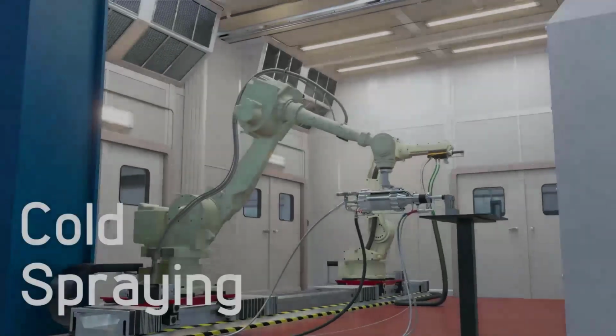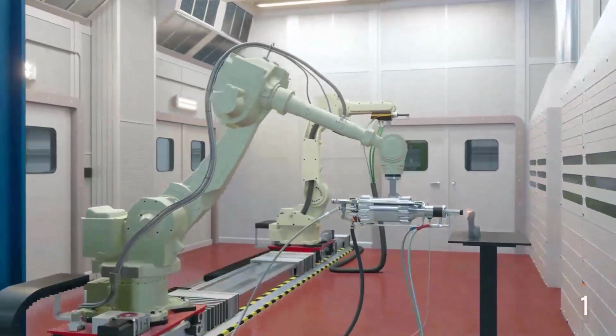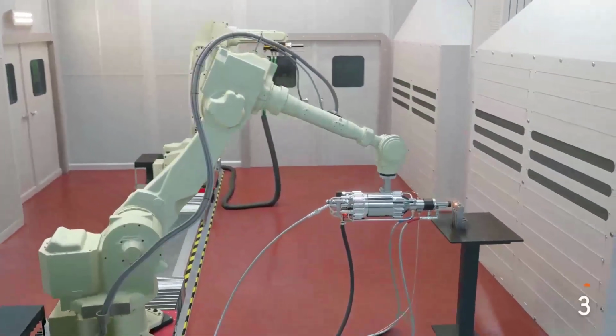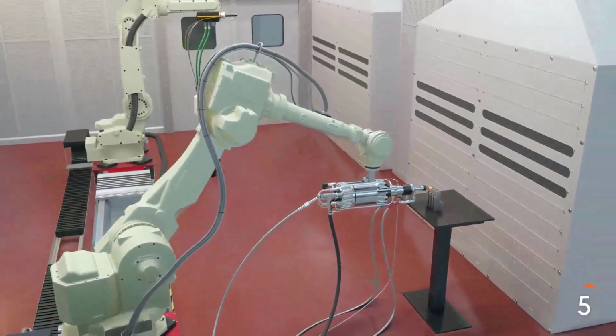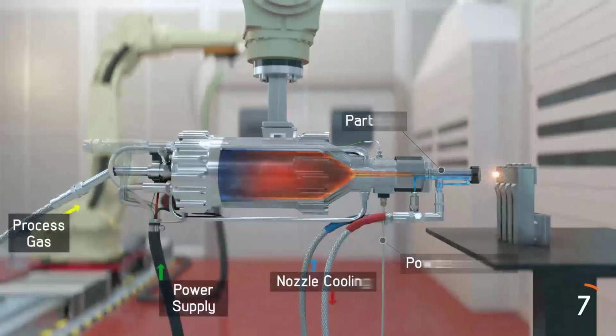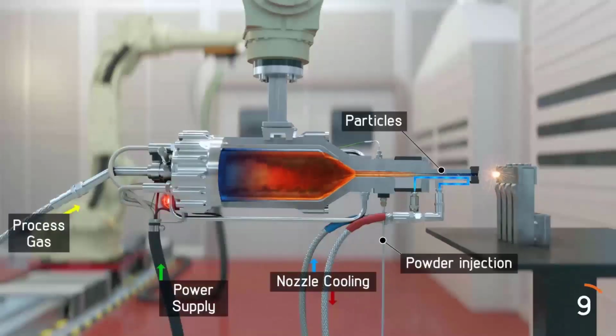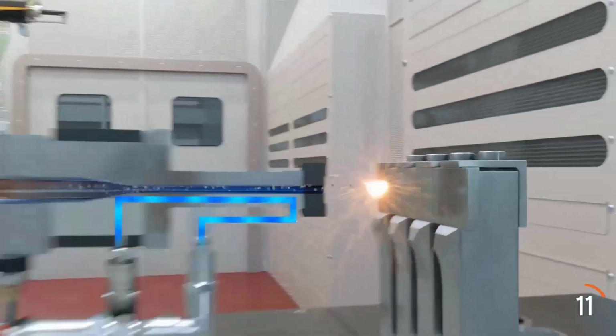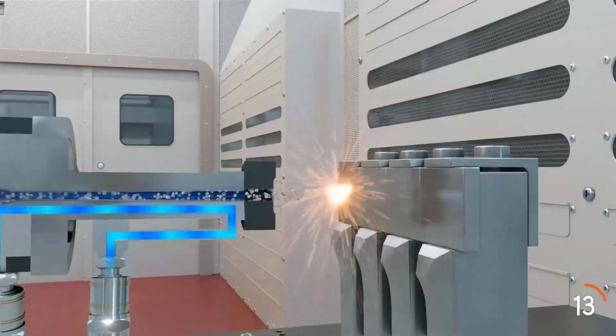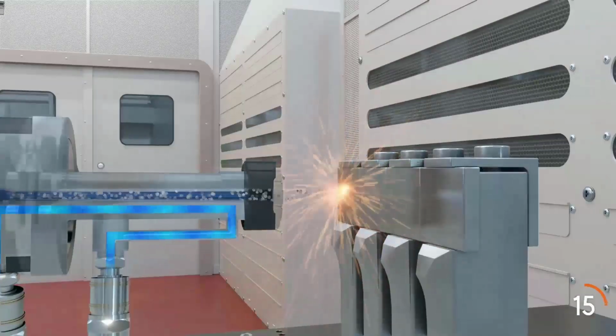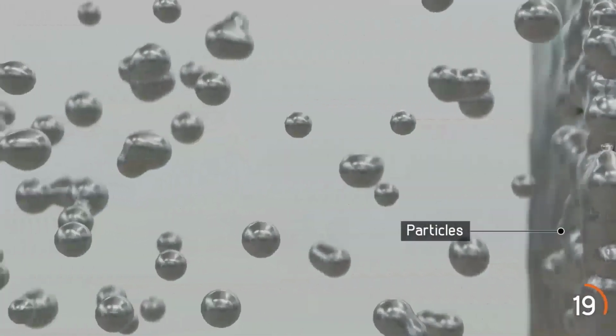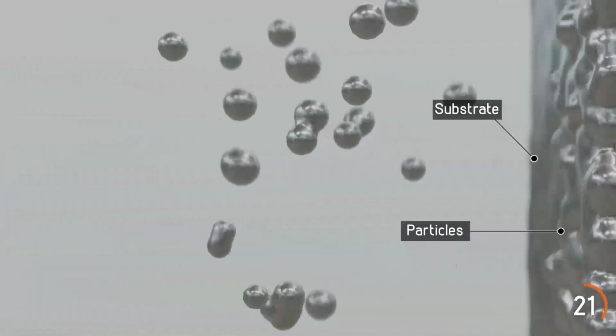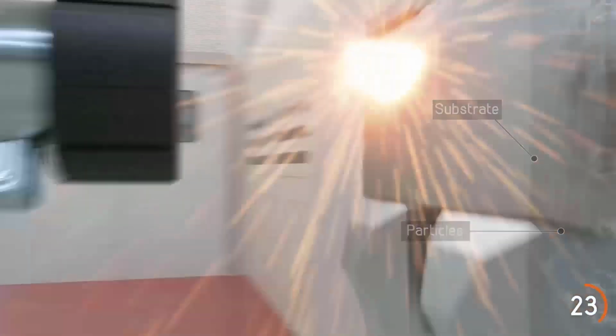Cold spray is a technique that allows metal powders to be deposited to form coatings, repair parts, or additively manufacture components. Powder particles are accelerated in a supersonic gas stream. Upon impact, particles deform rapidly, oxide layers are fractured, and a metallurgical bond can be formed. Particles remain within the solid state throughout the process, with minimal heat input to the substrate.